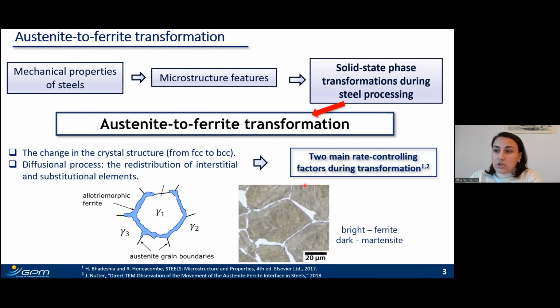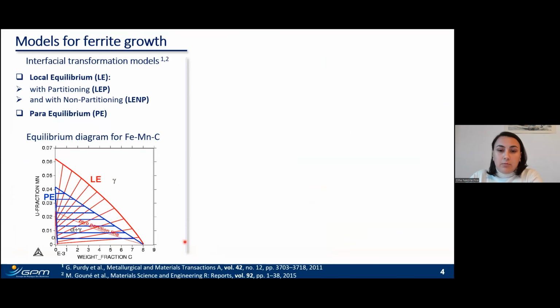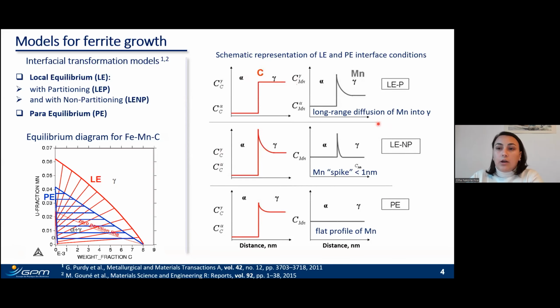And this phase transformation begins with the preferential growth of allotriomorph ferrite on existing austenite grain boundaries, with further growth that can be treated as one-dimensional planar growth normal to the prior austenite grain boundary. To describe this phase transformation, many different models have been developed, and the assumption of local equilibrium and para-equilibrium is one of the most widely used. This assumption belongs to the interfacial transformation models, and therefore they predict the existence of a certain compositional profile across the transformation interface that is schematically shown here on the slide.